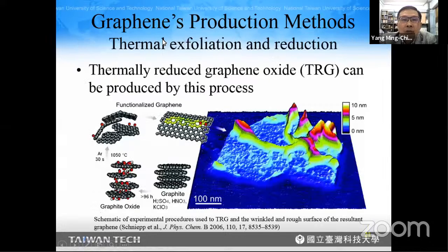And after talking about chemical reduction, now we take a look at thermal exfoliation and reduction. In this method, thermally reduced graphene oxide can be produced by this process. Here again, in the beginning, we also have the graphite. After treating with the oxidizer, it will become graphite oxide. So this is basically the same as the previous method. But after that, we use heat to reduce the graphene oxide. Here, it is conducted at 1050 degrees in an argon environment for only 30 seconds, and then we will obtain this graphene layer. And afterward, it will be disintegrated into monolayers.